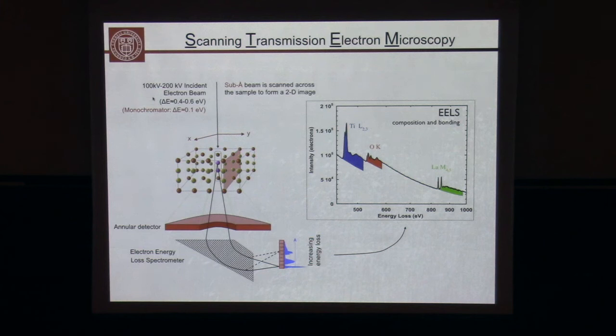So these inelastic scattered electrons will undergo an energy loss, and we can disperse that using a spectrometer and measure the number of electrons as a function of energy loss. What you see right away here, we can extract titanium, oxygen, and lanthanum. This is a lanthanum titanate sample. What's important is that the area under the curve correlates with the concentration of the material, but much more interesting is that the fine structure, the exact shape of that peak, will tell us how the bonding varies in the material. So how does hybridization affect it? What is the formal valence of our material?